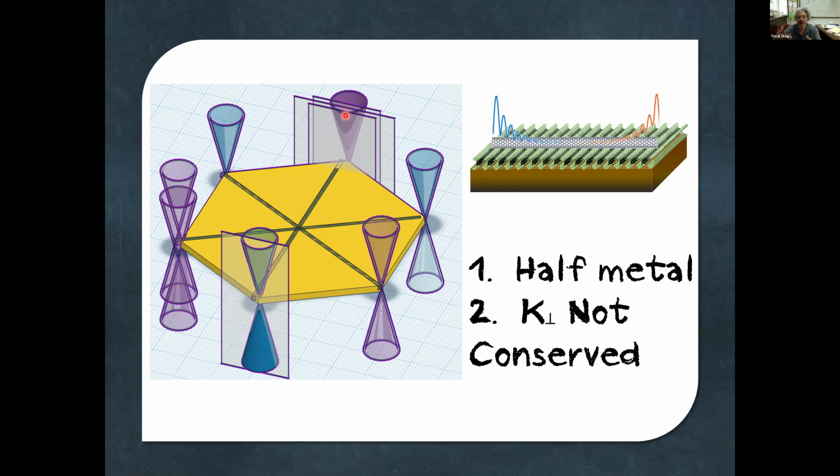These are numbers that we're not used to from indium arsenide or indium antimonide. These are huge numbers. So the important thing is that the spin-orbit coupling is such that the spins point out of the plane. And what holds them are huge forces with an energy gap of the order of 0.1 electron volt. So these materials are very special in that sense.